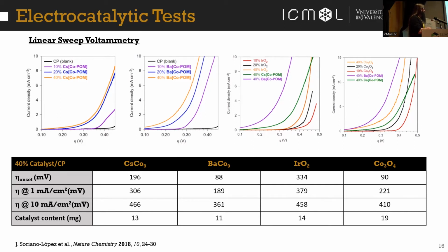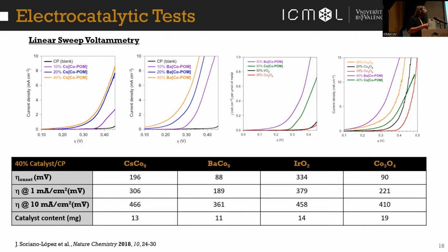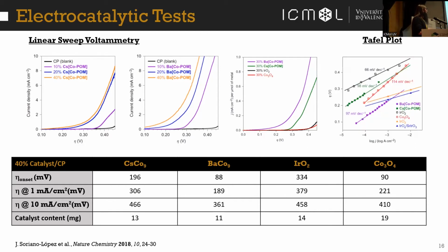In order to have a fairer comparison with these metals, we also compared the activity taking into account the amount of metals we had in each blend. Here we can see that the barium and the cesium salts of the cobalt-9 were much more active than iridium and cobalt oxide. We also compared the activities of these electrodes using a Tafel plot. The Tafel plot comes from the Tafel equation, where you measure the change of the current density against the overpotential. And this is a very strong tool for comparing electrocatalysts.